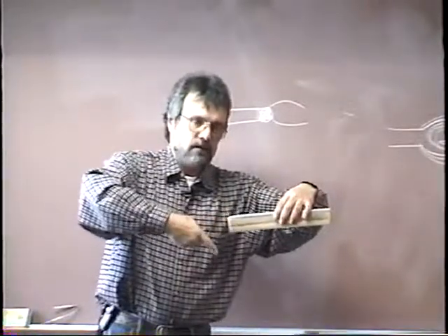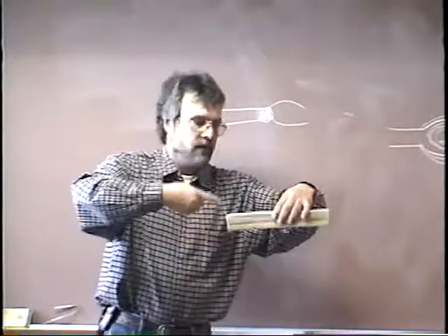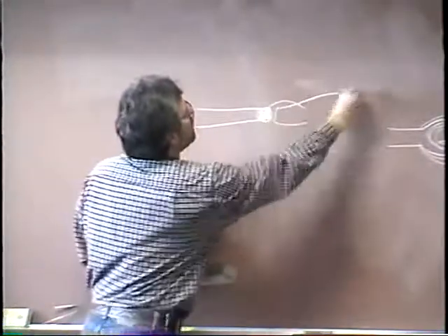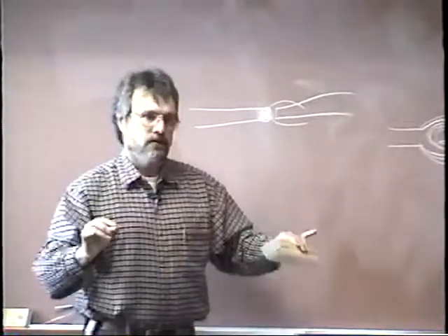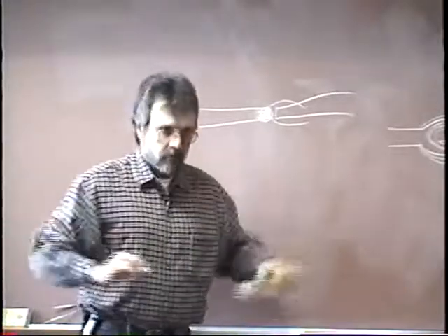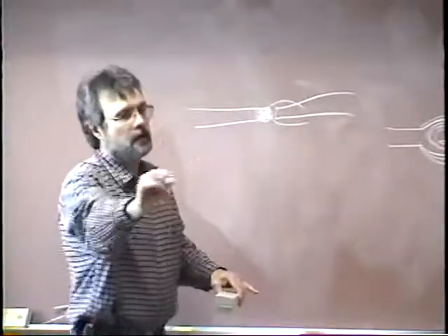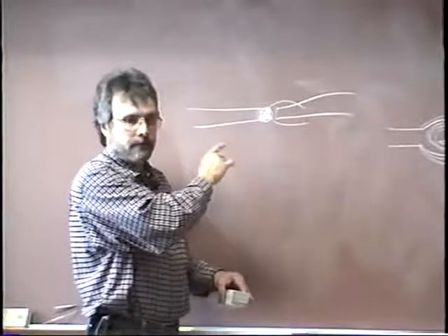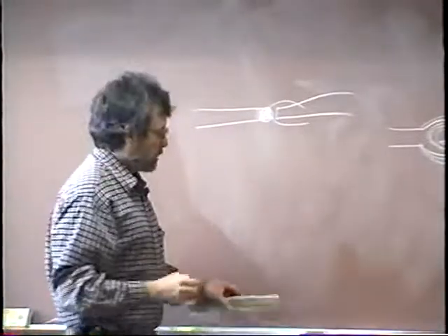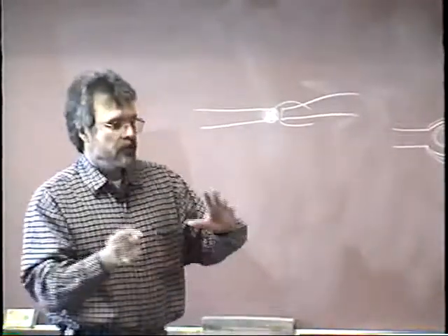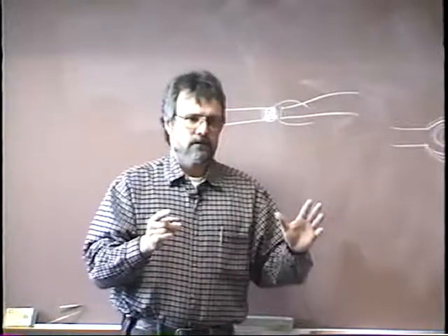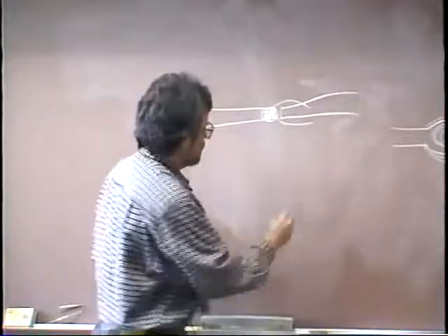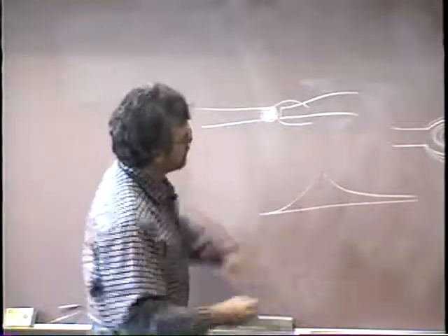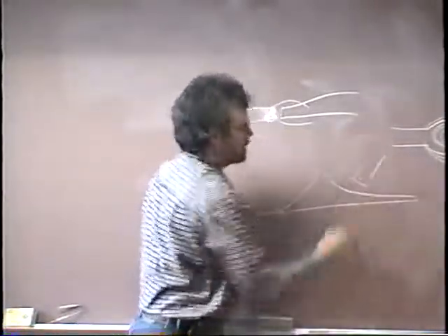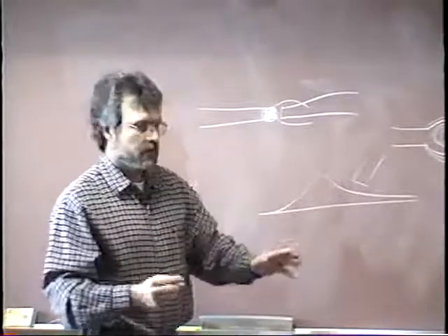If you can slice right through the end of the tip of that weld where you left off, get down in this keyhole with your electrode, and then pause for a moment, give everything a chance to tie in, and then take off, you'll get a good tie-in. And there's actually two ways that we do these root passes. One is on your tacks where we're going to blend them, grind them like this and come out slowly.